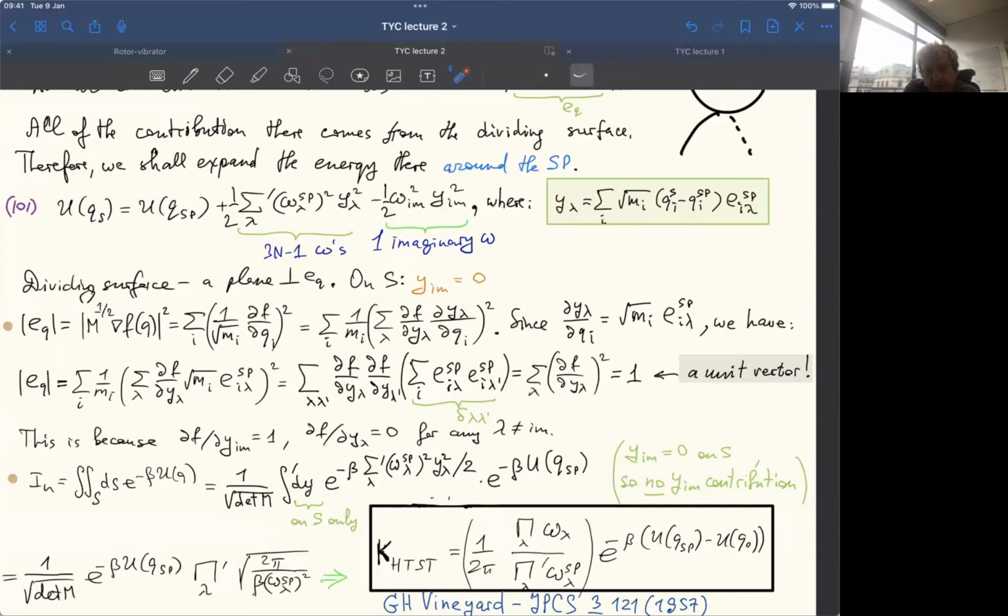This is not very easy to do because you need to localize this transition state and the minimum very, very precisely. Otherwise, you will get more than one imaginary frequency. But in some cases, this calculation can be done ab initio, and this way you will get access to the prefactor as well. So that's basically all I want to tell you.